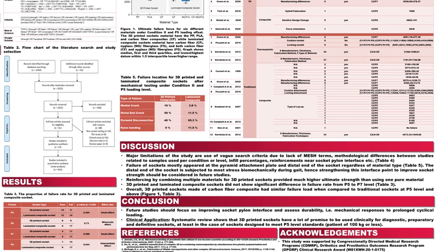So for the discussion, we found that the major limitation of this study is that there were a number of important differences between the studies, which makes it hard to draw a generalized conclusion. And as we saw that the pylon interface was the weakest point of the socket, strengthening this interface point should be addressed in future study. We also found that reinforcing the socket with carbon fiber provides much higher strength than PP and PLA. But these results only apply from P5 to P7 load level.